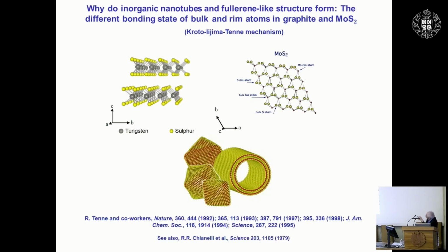If you look from the top, you see that there are many dangling bonds around this nanostructure of molybdenum disulfide or tungsten disulfide, and consequently, they remain unstable. If you heat it up to 900 degrees or so, they will spontaneously form nanotubes. And that's what we saw.